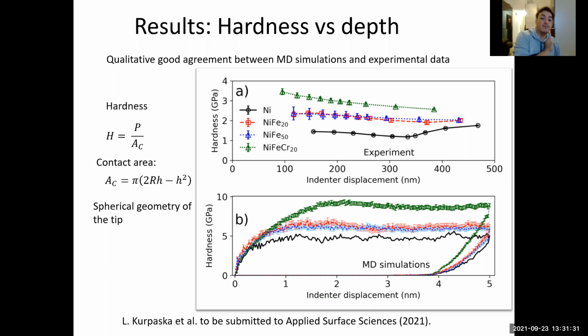But since now we have the mixture complexity for the nickel iron 20% and 50%, it is not enough to perform only one MD simulation. So we decided to perform around 20. It's enough for good statistics in the results. And these error bars show the maximum hardness out of these 20 MD simulations, and this is the minimum. So the hardness for 20% and 50% falls within the error bars, and it's the same for the experiments. Now we have here chromium, and we also performed 20 MD simulations. So this is a qualitatively good agreement between the experiments and the MD simulations.